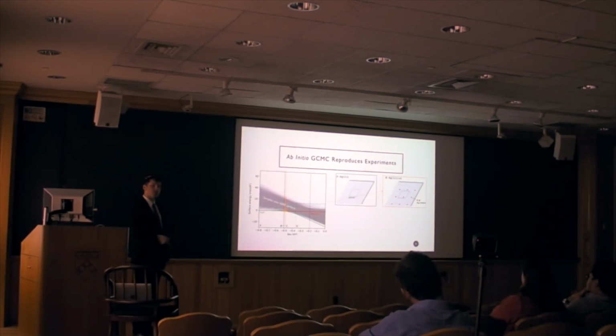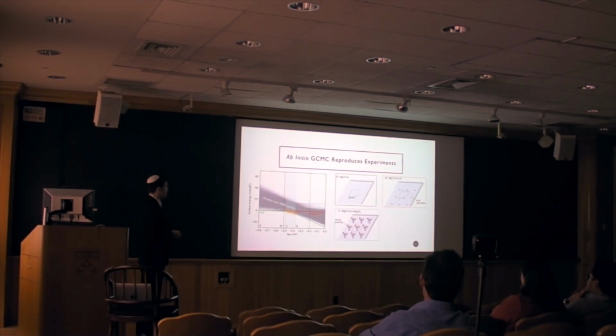If we increase the oxygen pressure further, we don't get more atomic adsorption. We actually get the formation of Ag3O4 pyramids. And this is much more stable than binding many oxygens on the surface. And also, the silver and oxygen can both come from the reservoir. And so we actually form these more isolated Ag3O4 pyramids.